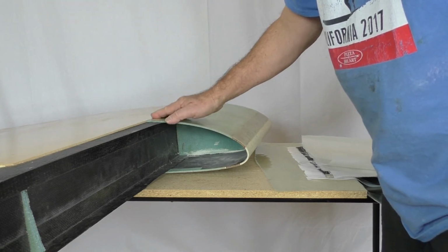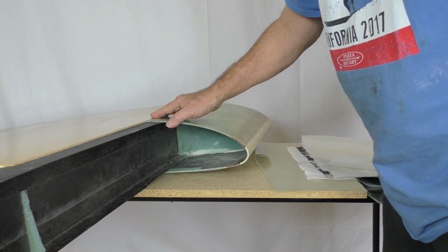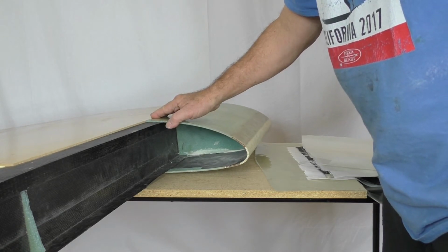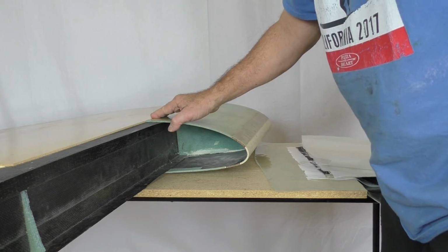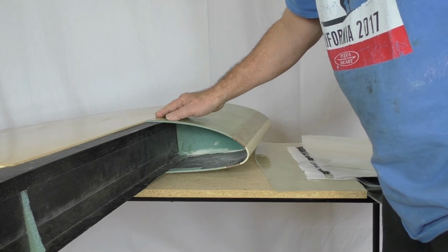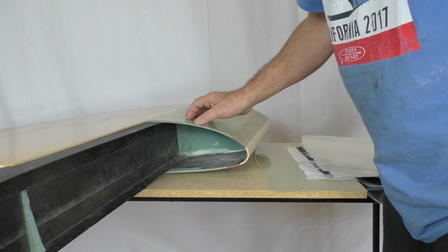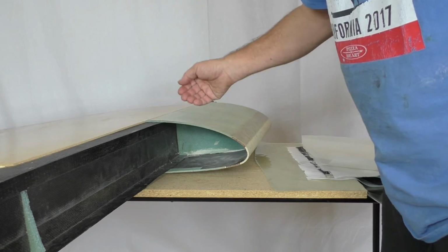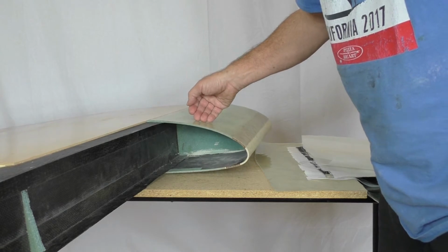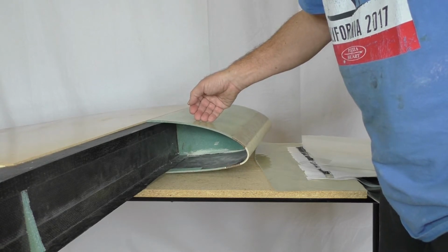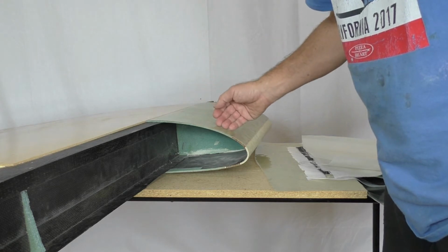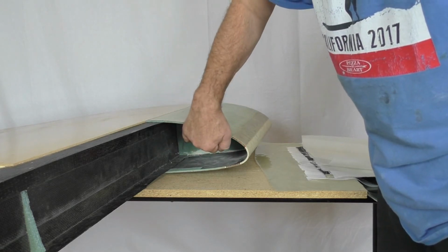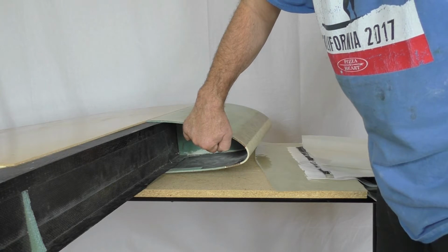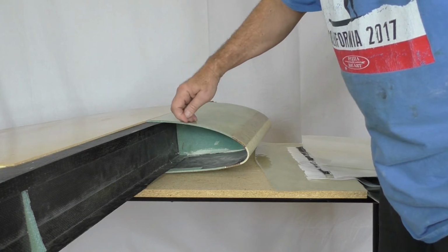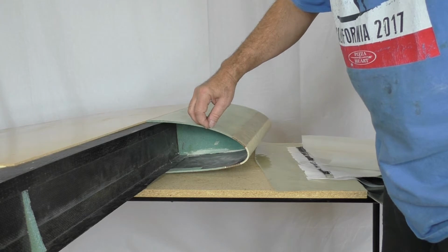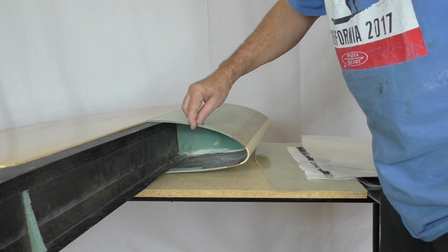So this D-tube is probably the most critical component of the structure of the aircraft. It must be made accurately and must have a very high strength to weight ratio. What you see here on this sample is an early D-tube that I made experimenting with different construction processes. The outside is a 3-ounce E-glass woven in a 120 format. It gives a very smooth finish on the outer surface. The inside happens to be 5 or 6 ounce carbon fiber. In between the two layers is 1/8 inch thick Divinycell foam. It's 3 pounds per cubic foot for that foam.